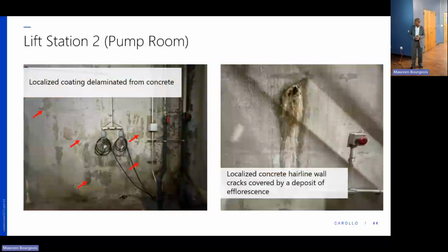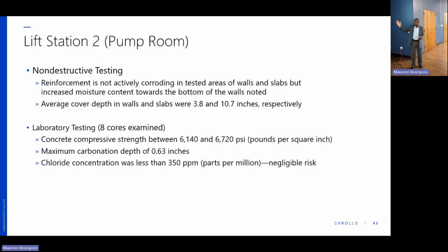What did the non-destructive testing reveal? No active corrosion, but it also showed that there's a lot of moisture at the bottom. In the previous picture that I showed, we saw that water ponding, so it captured that it's very moist at the bottom. The cover depths that it measured with our equipment were 3.8 at the walls, 10.7 at the slabs. We want a minimum of 2 inches, and so that was good. We also tested 8 cores here. We are in the 6,000 range for the compressive strength, well above our 4,000 mark for concrete, and so that is good. Carbonation is at 0.63. We have enough cover to accommodate that, and the chlorides here are also negligible.